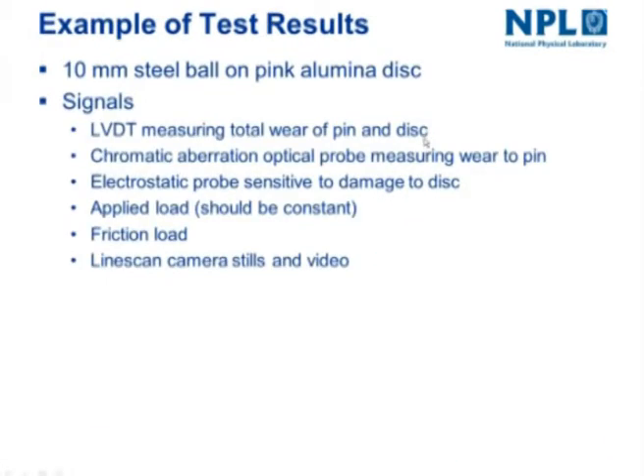So there's an example here of a test, 10mm steel ball on pink alumina disc. These are signals we looked at. LVDT to measure the total wear of pin and disc. We have something also called a chromatic aberration optical probe. These are very nice devices. They can run very fast, up to 100 kHz, and give you very accurate measurements of displacement. We've got an electrostatic probe. We're measuring applied load, we're measuring friction load, and as I say, line scan camera, stills and video.